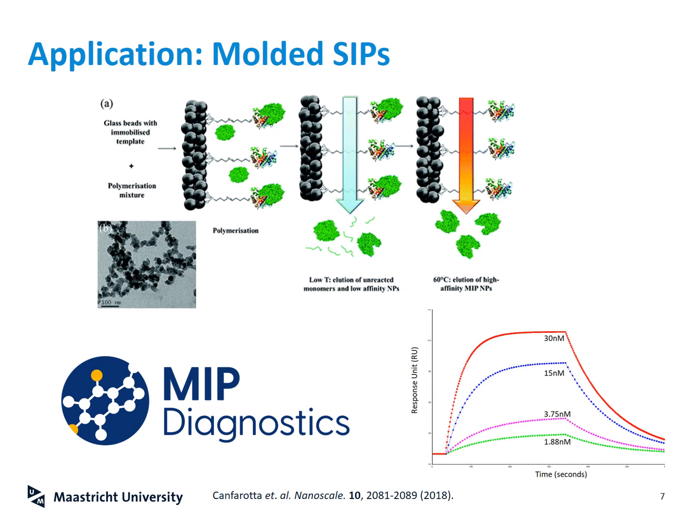the MIPs with a very low affinity for the target will come off the column. They basically will throw these nanoparticle MIPs away because they don't have much affinity for the target. Then they will add a solvent or water at an elevated temperature to break the bonds between the protein, the target template, and the forming MIPs. And these MIPs will be the high affinity MIPs that they actually use.